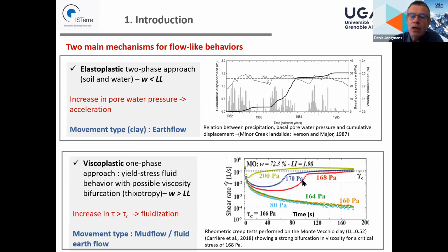168 Pascal. And the point is that sometimes this evolution is gradual and sometimes it's very abrupt, like you see here for this Montevecchio clay. And in this case, we speak about a viscosity bifurcation, which shows the thixotropic behavior of the clay. And the classical movement type associated with that is a fluid behavior, which can be described as mud flow or as the fluid earth flow as described this morning.